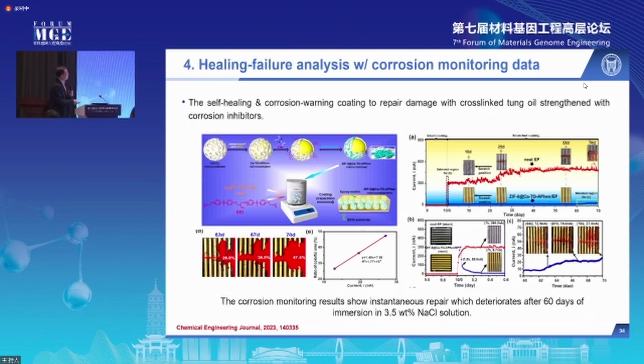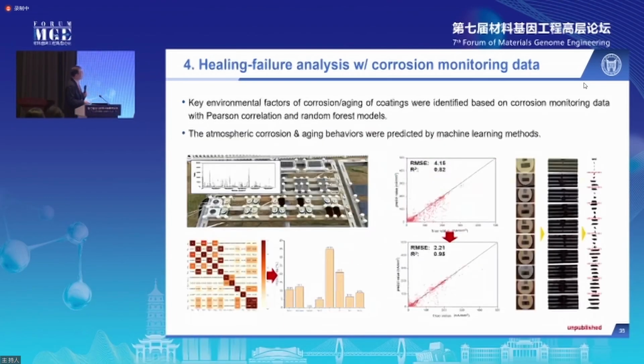And this is another example showing the self-healing coating under immersed condition, how it heals and how it degrades over time. And of course, we have also combined machine learning to process the data from the corrosion monitoring test on self-healing coatings, and we can identify what environmental parameters will give the best self-healing actions, and also predict the service life of the self-healing coatings in a real environment.